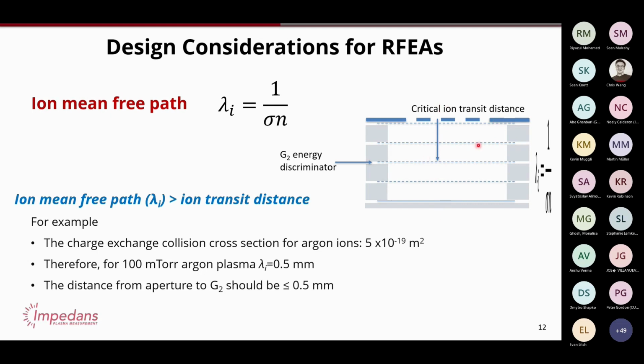Because this is obviously not an absolute vacuum. This is at the same pressure as your chamber. It has lots of neutral gas in here from the chamber. So you must make sure that the mean free path of ions is larger than the distance between the surface of the sensor and the discriminator grid. Now, after the discriminator grid, if a collision happens, it doesn't matter as long as we collect the charge on the collector plate. So that means typically this is really on the order of less than a millimeter, a few hundred microns.